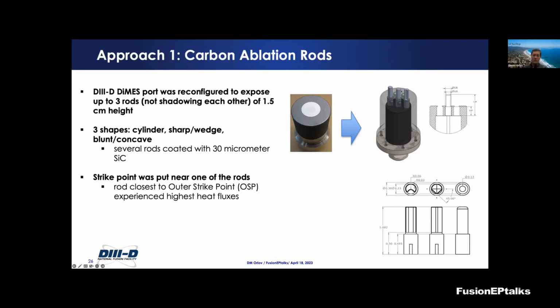So we designed and built this head, and located it next to the outer strike point in the DIII-D tokamak, usually where we have the highest heat fluxes. We also had a few rods with 30 micrometer silicon carbide coating. If anyone's interested in those results, I can show them—I have them in the backup slides.